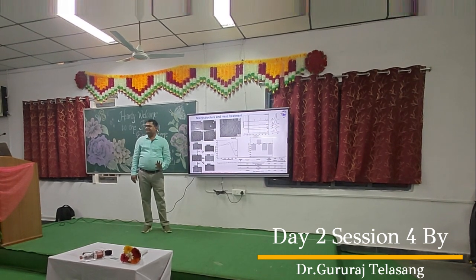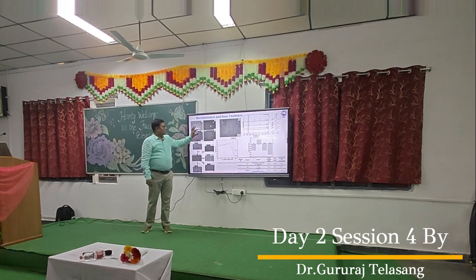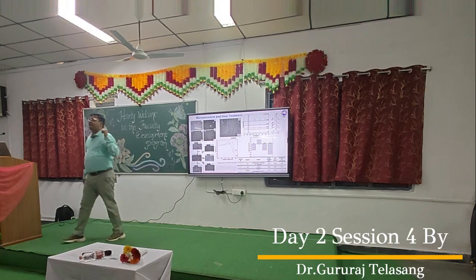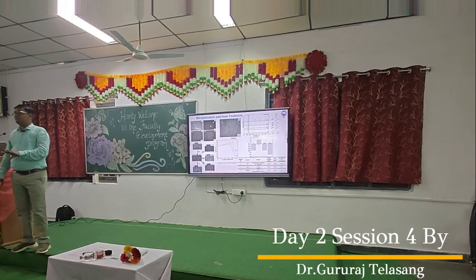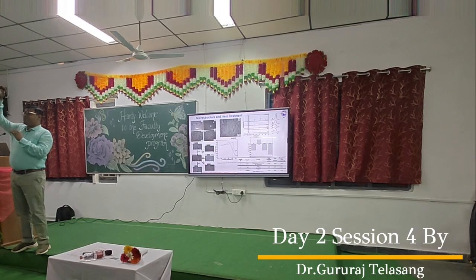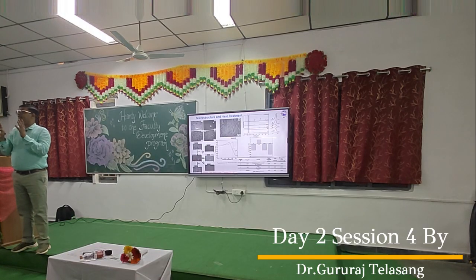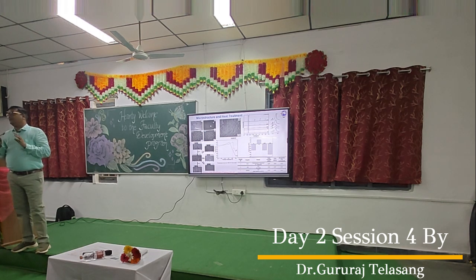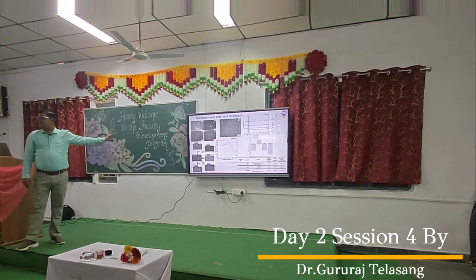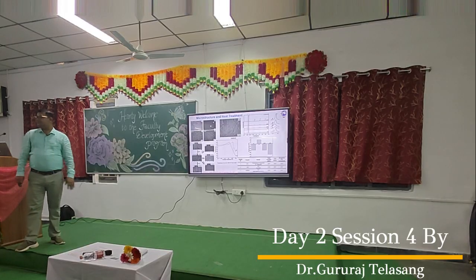Heard dendrites? Okay. So this is an equiaxed dendrite, this is a columnar dendrite. But this is not okay for my application because this is a segregation of phases. So that is not good for what I am doing here. This is an H13 tool steel pressure die casting die. It's thermomechanical fatigue. The die will go from 200 degrees to 750, then 200, then 750, 200 in 30 seconds, with a load of aluminum melt pushing inside at 200 to 250 MPa. So that is thermal and mechanical cycle fatigue. These kinds of segregated microstructures will not do, it will crack and break catastrophically.